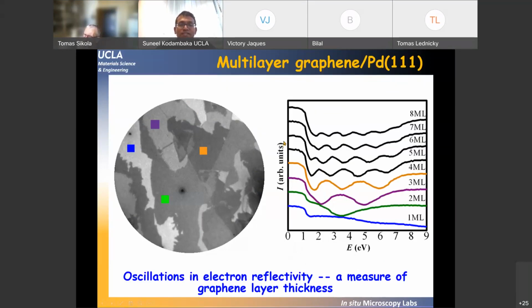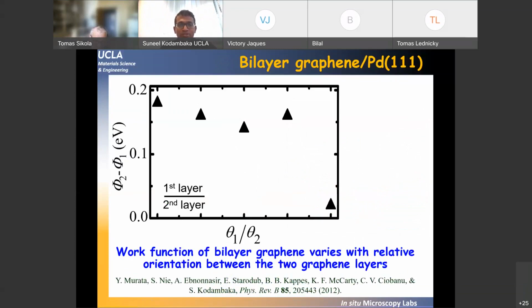And once again, you can use reflectivity curves to identify the number of layers you have within a given region. And so these colors, the purple, blue, green, and orange colors here correspond to reflectivity curves from different layers. And this electron reflectivity, the number of bumps you see is mainly because of the interference at the reflections at the interfaces. And so you can measure the number of layers from these reflectivity curves. And not only that, you can also use the reflectivity data and combine it with the LEED patterns, low energy electron diffraction patterns, to get surface work function as a function of layer orientation and layer thickness.